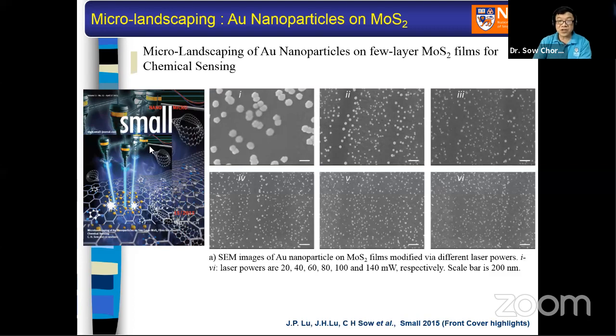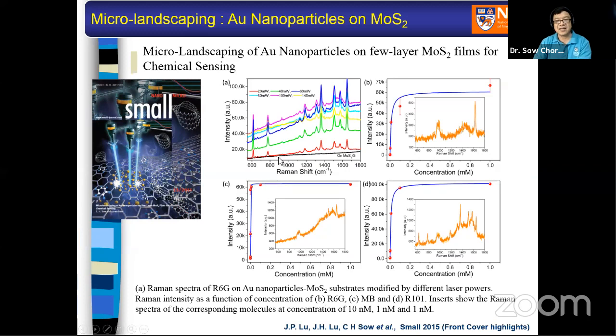And the magnifications of all these pictures are the same. See, the scale bars are the same, 200 nanometers. The beautiful thing is just by changing the laser power of how you perform this process, you can tune the size of the gold nanoparticle on the surface of this MoS2 film. So we use it as a tool to do all kinds of chemical sensing, and then of course it creates interesting, beautiful diagrams. So it becomes a nice detector in terms of surface enhanced Raman spectroscopy for chemical detection.